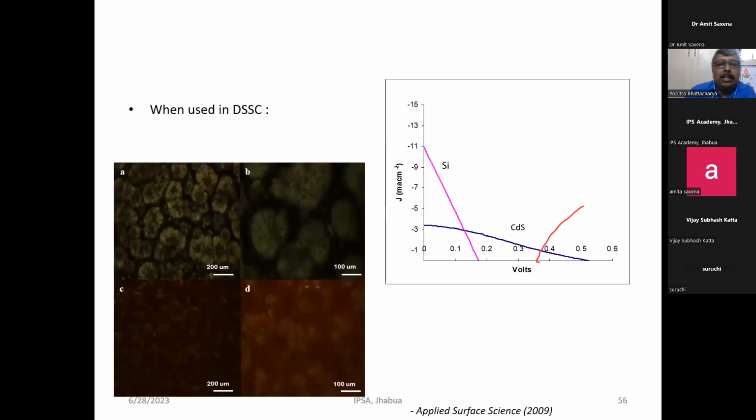But interestingly, when they were used in the solar cell and the cell was illuminated, the silicon or cadmium sulfide particles, the semiconducting particles, form a conducting pathway and it becomes almost ohmic. The conducting pathway gives very high current, but not VOC. Therefore, the use of filler, especially semiconducting filler in polymer electrolyte, may not be very encouraging in the case of solar cells.